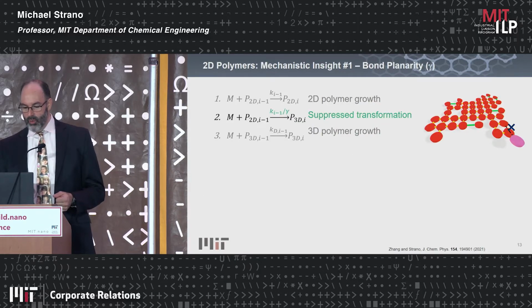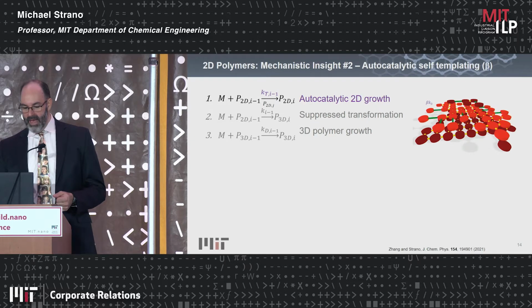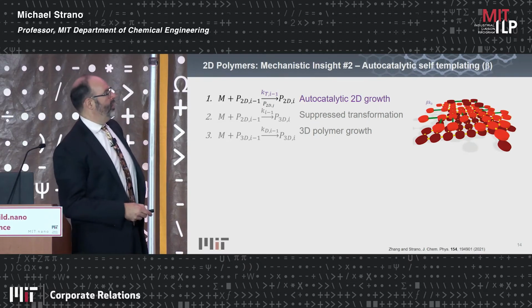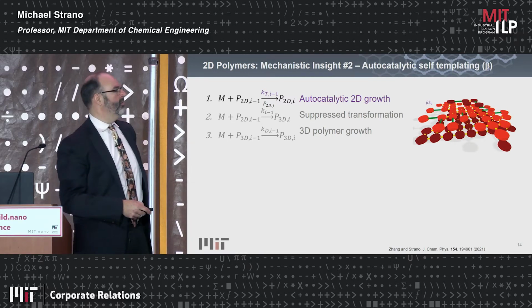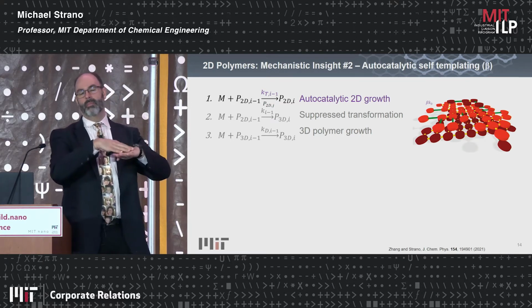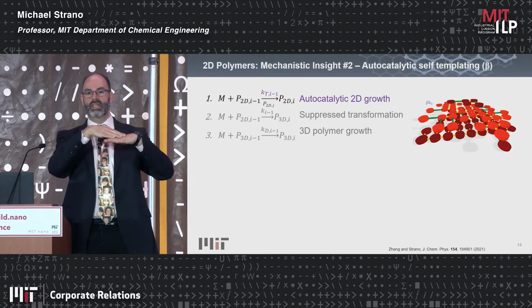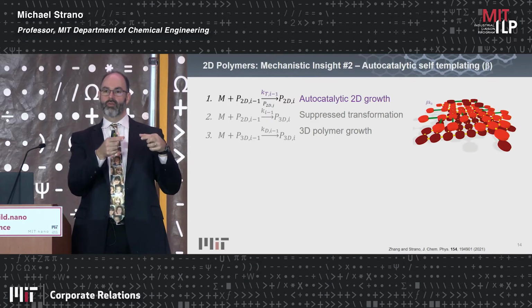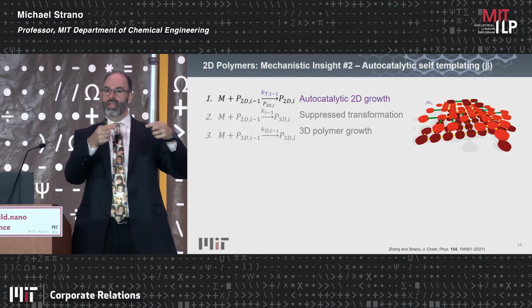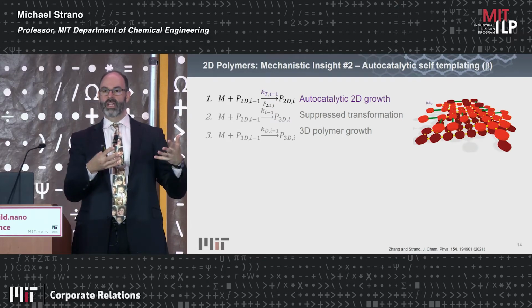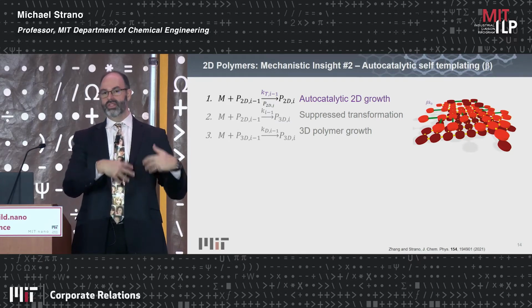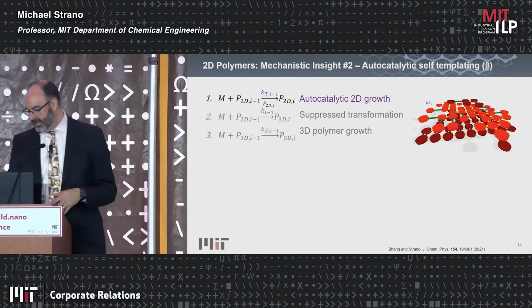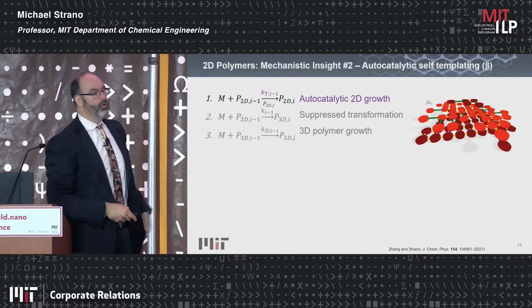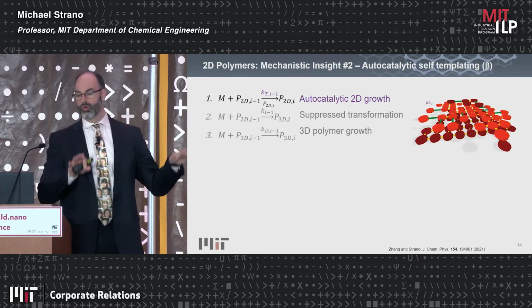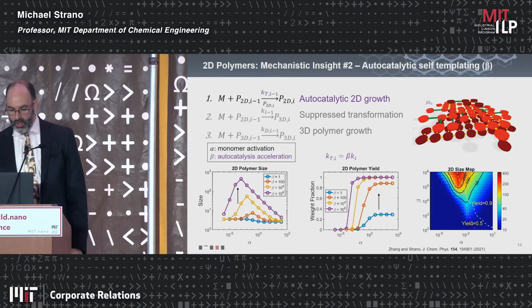It turns out that we discovered a mechanism by which you can get around this. And we call it autocatalytic templating. Basically, a little growing seed of a 2D material that does form before it grows out of plane can template a monomer. So a monomer can sit on the growing seed and be held in place so that it can then polymerize in 2D. And in that way, materials can actually help each other grow. So it's autocatalytic, means the material itself is a catalyst. It helps itself to grow, and it's auto, so it's autocatalytic templating. And you can show you only need a little bit of this to happen, and you can grow polymers in this way. So it's a completely new game changer.